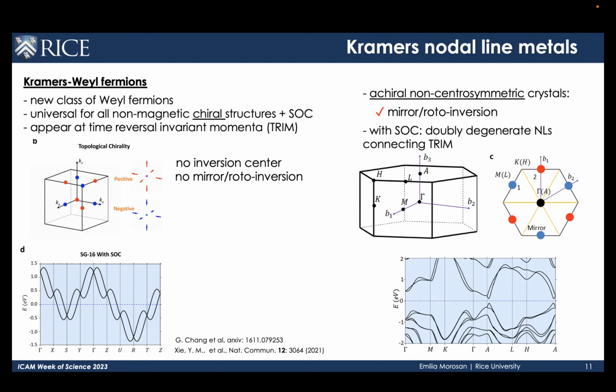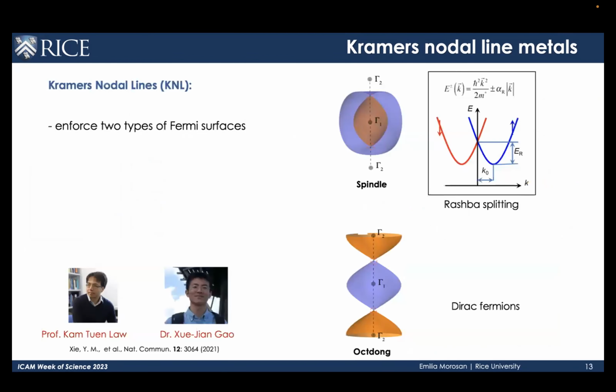And so coming back to the motivation of where do we look for such physics? Well, let's look at achiral non-centrosymmetric crystal structures. And theoretically, again, the prediction goes further to say that there are two types of Fermi surfaces that can produce these Kramers nodal lines, the so-called spindle, which in a cut across this Kramers nodal line can have something like a Rashba splitting, or an octdong, which looks like this, which has these Dirac points, or Dirac fermions.